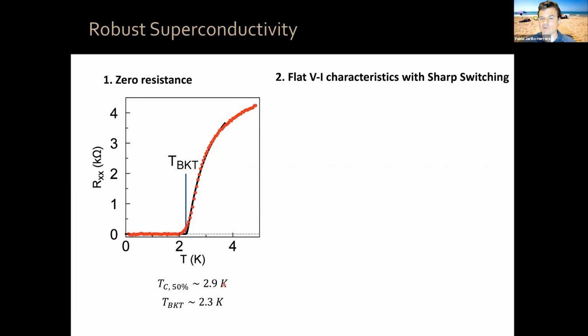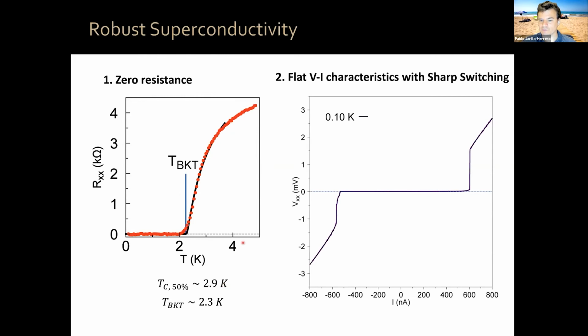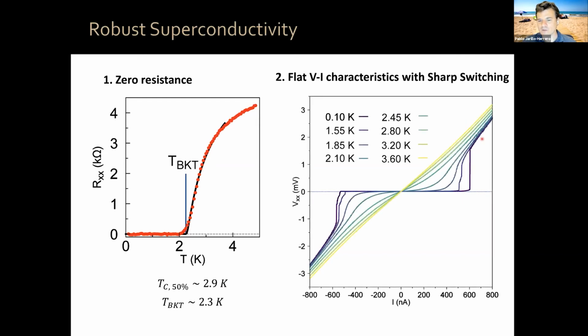Now you want to see flat voltage-current characteristics with sharp switching. And indeed, you can see here that you have a finite critical current with zero voltage dissipation, and then it switches abruptly to a normal state. You can do this as a function of temperature. You can analyze this to obtain independently the BKT temperature, which agrees with these measurements.